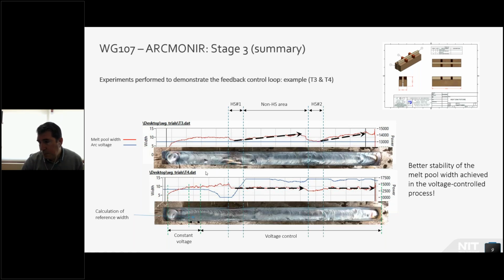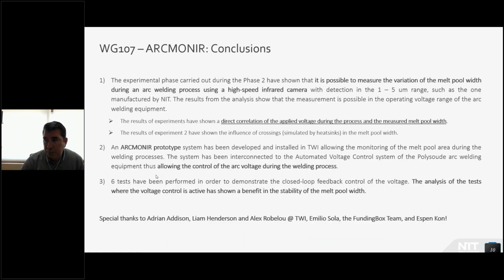Here we can see more clearly with the photos of the two processes. Here we can see that there is an area where it seems to have a lot of arc intensity, but clearly you can see that the melt pool is increasing in these areas when there is no control after the two heat sinks, whereas in the controlled process the melt pool width remains constant. This leads to a better stability of the melt pool width, which has been achieved with the voltage control. So just to summarize, in the experiments we have demonstrated that there is a direct correlation between the voltage applied to the arc and the melt pool width measured with the camera that we are using.